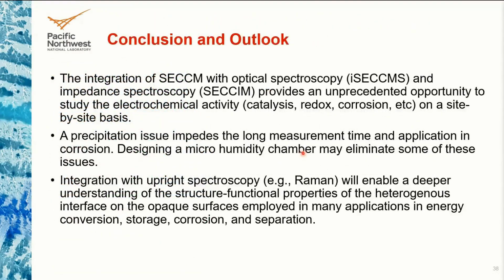So as a conclusion of today's talk, we successfully integrated the SECCM with optical and impedance spectroscopy, which enables us to characterize the electrochemical activity on a site-by-site basis. The precipitation issue still exists, and designing some micro humidity chamber may eliminate some of this issue. And integrating with a spectroscopy technique like Raman would also enable more structure-function relationship measurements for opaque surfaces, because so far we have done it only for indium tin oxide, which is a transparent surface.